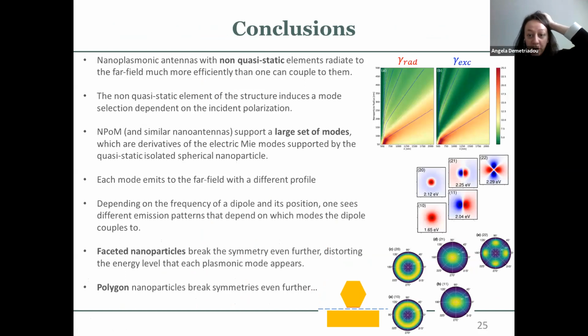So to conclude, when you have non-quasi-static elements in a plasmonic nanoantenna, in a plasmonic system, then you start seeing that it can radiate to the far field a lot more efficiently than you can couple energy into a quantum emitter that exists in the system. Also, if you're going into very small gaps of just a few nanometers, it is important that you do not ignore higher order modes. Such systems support a very large set of modes that are not insignificant, and they start actually affecting what you observe in the far field, what you measure experimentally, and they change the emission.